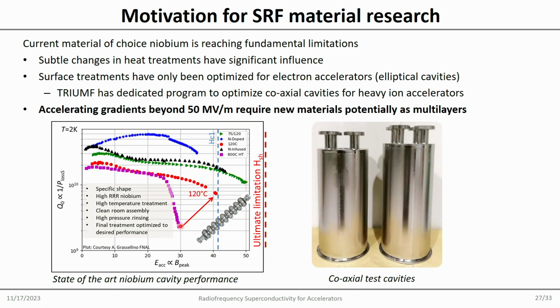I mean, this is not economical just to operate it. You really want to be around there, the 10 to the 10 range, because you need cooling. And then, one thing is if you just bake it 4 hours at 75 degrees and then go to 120, you go here. You put in a little bit of nitrogen in the process. So this is all very small, subtle changes to the whole preparation process which have a huge effect on both quality factor and accelerating gradient.